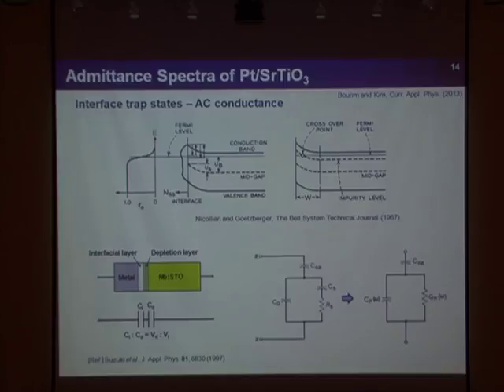In our Schottky junction case, we already know that an interfacial layer can exist. Dr. Hall also mentioned this issue yesterday, and there's an old paper. We also found that our device really has an interface layer from its CV characteristics. To explain the built-in potential, we should include the interface layer, so even Schottky junctions can be modeled by this kind of equivalent circuit.